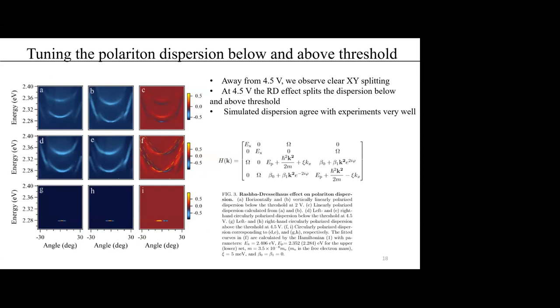I believe this is very challenging to realize in common microcavities. So if we measure the polarization of the dispersion, we can see that when the voltage is 2 volts, the dispersion of the perovskite microcavity shows clear X and Y splitting. The Rashba-Dresselhaus effect can be observed when the voltage is 4.5 volts.